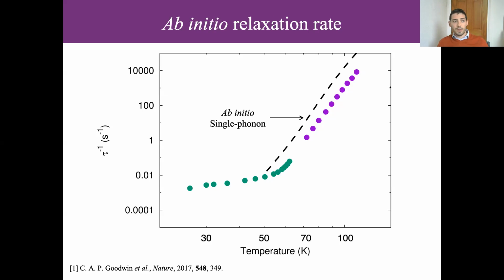Essentially, in reciprocal space, you can think about the different unit cells. In real space, we start talking about propagation of phonons as plane waves through crystals. So with different wave vectors, that's how different unit cells are doing this motion periodically, or which direction a given phonon is traveling through a crystal. Same sort of stuff, you get different energies. And so how these curves change energy as a function of wave vector is also important.